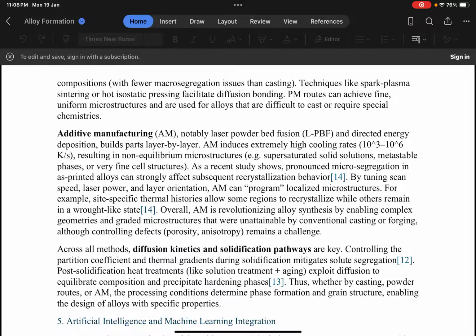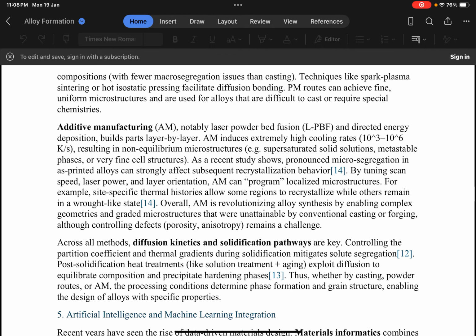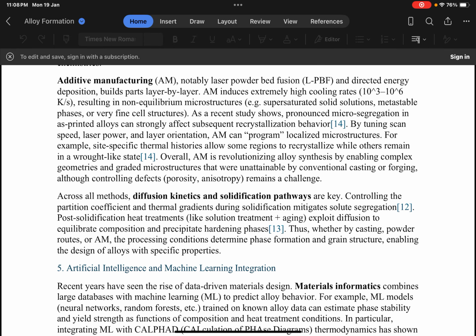Overall, AM is revolutionizing alloy synthesis by enabling complex geometries and gradient microstructures that were unattainable by conventional casting or forging, while also controlling defects. Porosity and anisotropy remain a challenge. Across all methods, diffusion kinetics and solidification pathways are key. Controlling the partition coefficient and thermal gradient during solidification mitigates solute segregation. Post-solidification heat treatment like solution treatment plus aging exploits diffusion to equilibrate composition and precipitate hardening phases. Thus, whether by casting, powder routes, or AM, the processing condition determines phase formation and grain structures, enabling the design of alloys with specific properties.